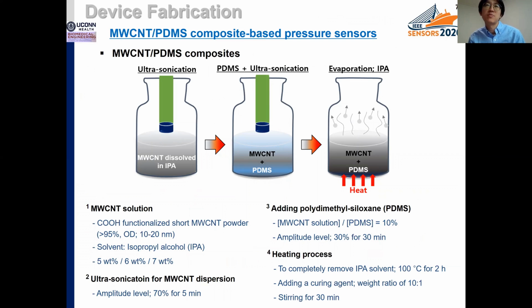This slide shows the device fabrication process. As you can see in this schematic, to fabricate MWCNT PDMS films, firstly, an MWCNT solution was prepared by dissolving carboxyl-functionalized MWCNT powders in IPA solvent. And then ultrasonication was carried out to disperse the MWCNT in the solvent. After that, PDMS was mixed with the MWCNT solution using ultrasonication for 30 minutes. Afterwards, in order to remove the IPA solvent, a heating process was carried out at 100 degrees for 2 hours and then